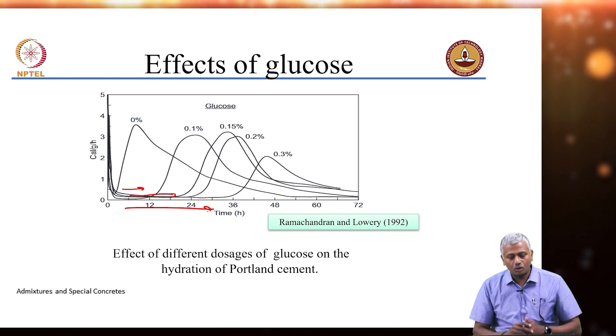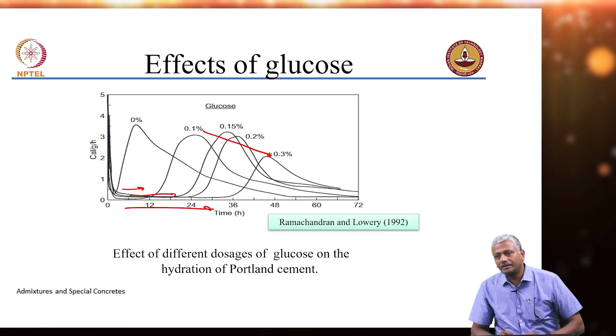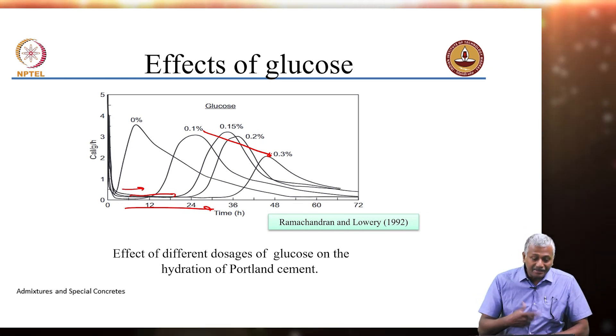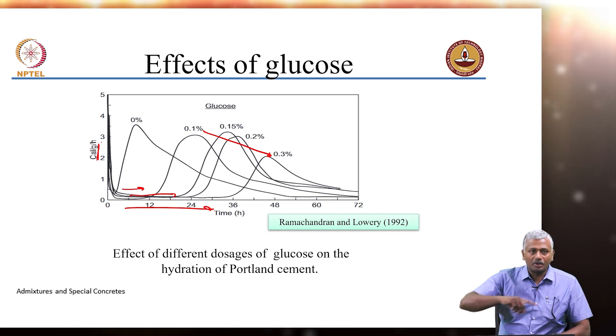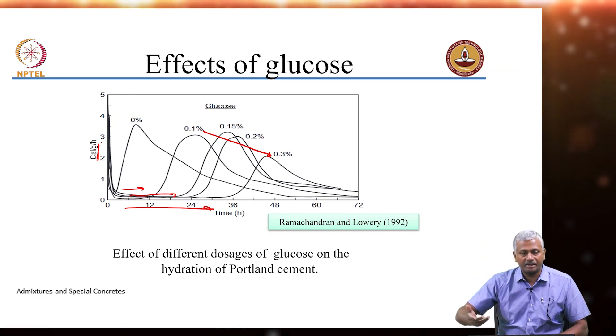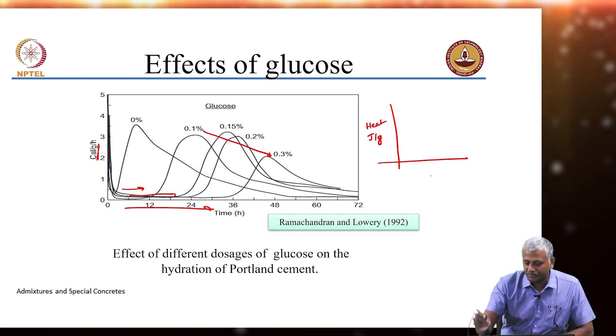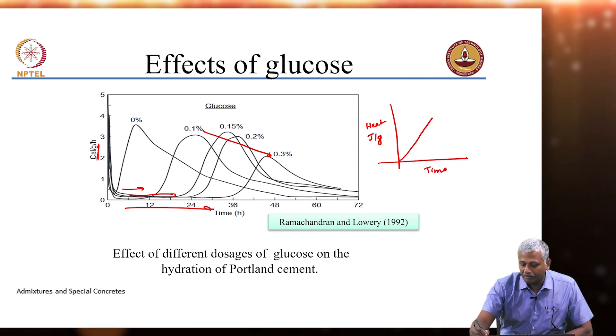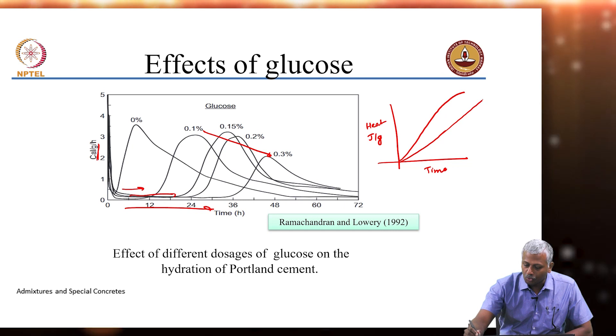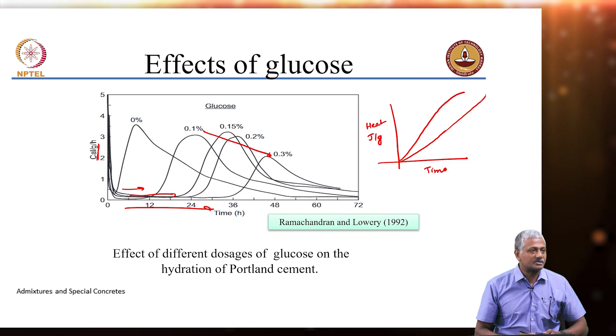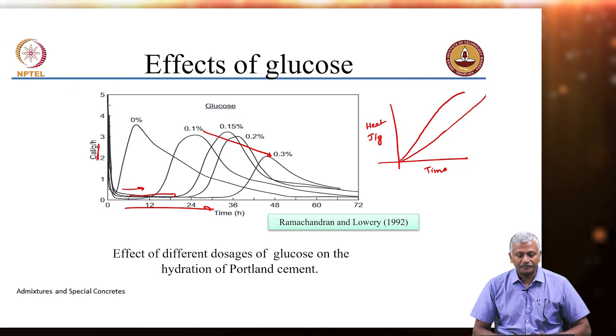It may also turn out that the actual peak heat liberated in the system starts getting reduced as more retarder is added, because the rate of heat evolution — calories per gram per hour — is represented by that peak, not the total heat evolved. Total heat evolved depends on how much reaction actually takes place; with retarded concrete the slope is gentler but ultimately reaches the same level. The peak heat rate may reduce when more retarder like glucose is added.